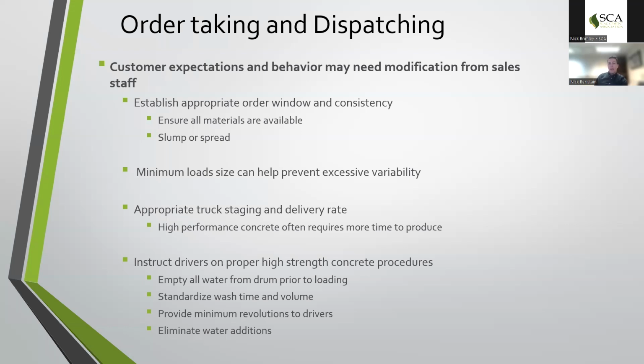We've often seen mixing times for some high performance concrete that require 2 to 3 mix minutes in the plant itself, and then another 5 within the truck, just to ensure the product is consistent and there's no variability in the load itself. To also support that, we generally provide minimum revolutions to the drivers. It's both stamped on their ticket, or now in the case of electronic tickets, displayed on the electronic ticket, so they have quick reference and they're not having to remember each time.